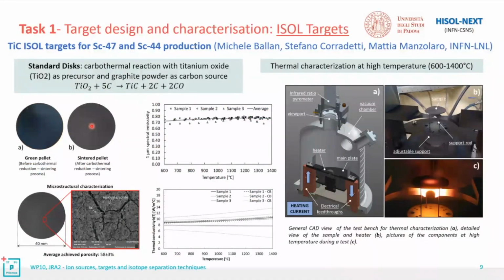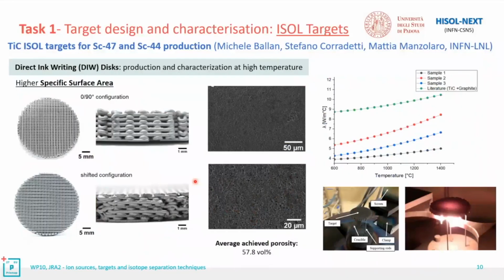It's a titanium carbide characterized by low density and was completely characterized at high temperature. In particular, here you can see the measurement of the emissivity and the thermal conductivity we made. This is the reference material for our ISOL target architecture, so we actually have these disks. But in the second part of PRISMAP, we wanted to improve the characteristics of this material. In particular, we wanted to improve the release properties that are very important for scandium beam production, and we also wanted to improve the capability to dissipate heat by thermal radiation from this material.